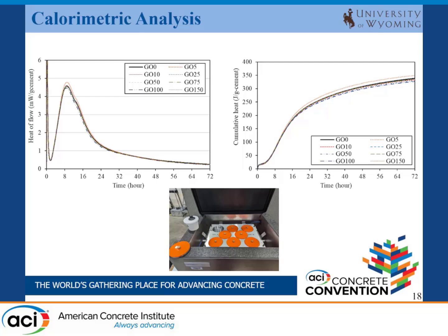We also did calorimetric analysis to find out whether the introduction of graphene oxide alters or creates any other peaks or any change of the peaks. But fortunately, we found that there is not much change in the heat flow and also the cumulative heat diagram. But we saw some increment in the peak for graphene oxide at 0.05% in the concrete.